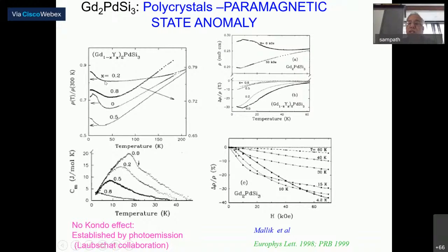Is this typically what is in a Kondo lattice? In a Kondo system, you take a cerium compound Kondo lattice, dilute it, you will keep seeing the minimum. And then you measure heat capacity above the magnetic ordering, a very huge tail, and even if you dilute, the tail still persists. This all suggests it is behaving almost like a heavy fermion.